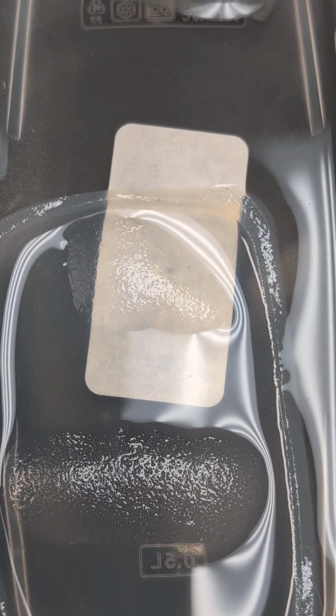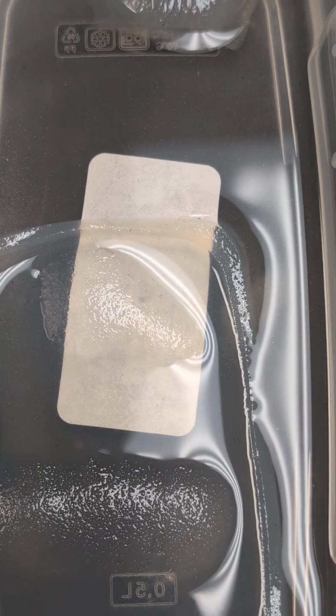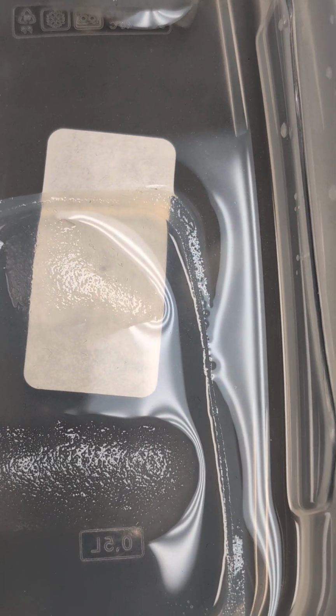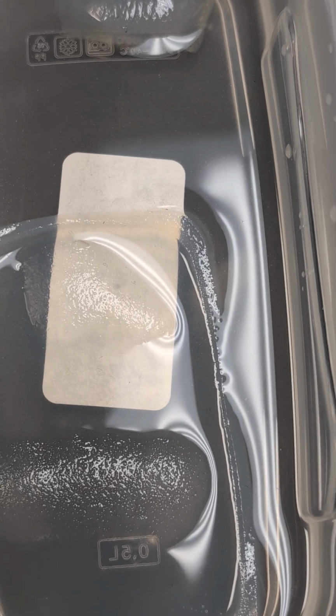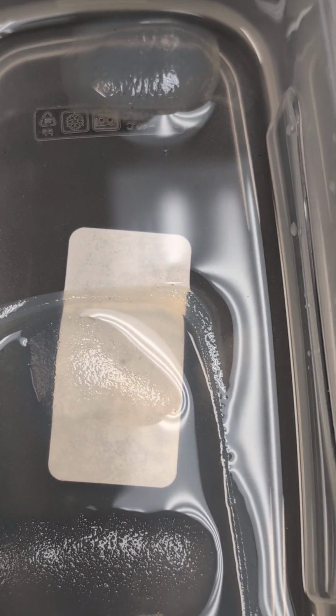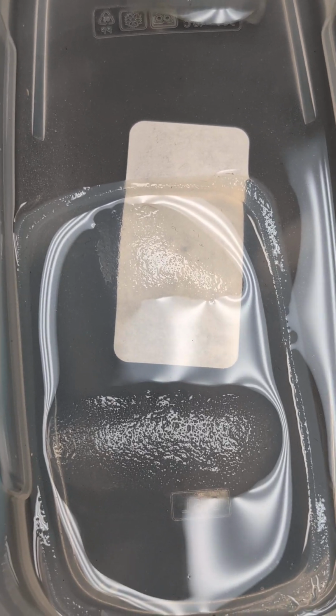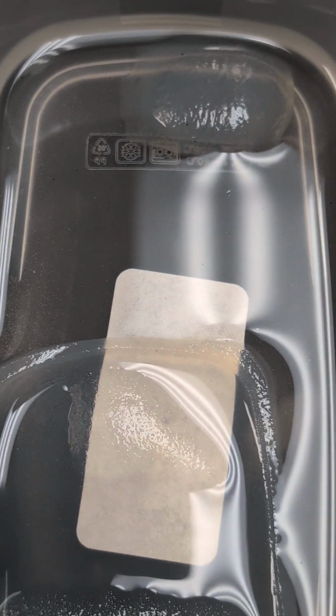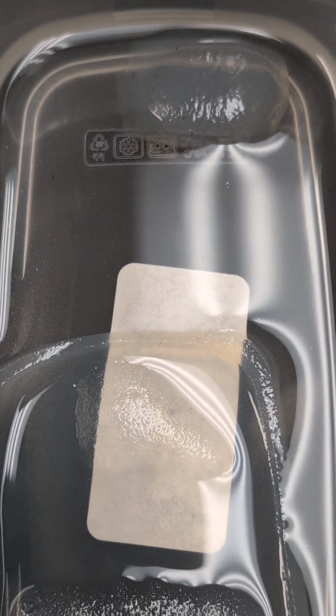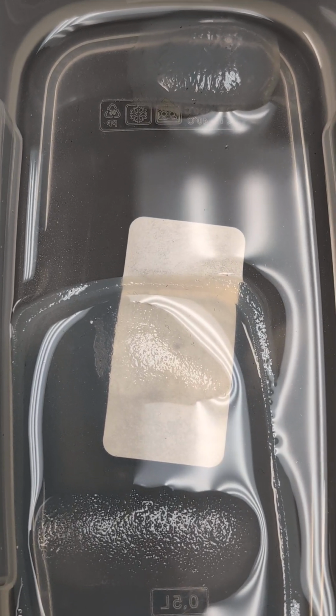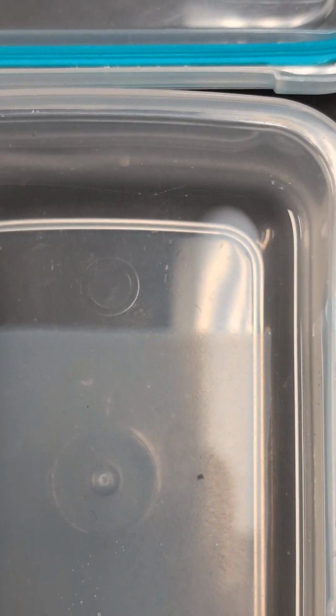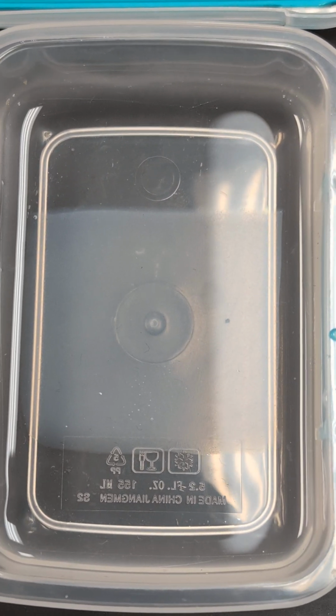And what's interesting with the glutaraldehyde, the chemical reactions between the Agar Agar carbohydrate alcohol groups, OH groups, and the dialdehyde, glutaraldehyde, you're forming hemi-acetal and acetal linkages. They're reversible, and the important thing is the pH range. Now, this solution, when we first put it together, was about pH 3, the bath. So I brought that up to pH 6 using litmus paper, pH 6. And I think you want to stay pH 5 to 6.5. If you're too acidic or too alkaline, you're not going to get really too much cross-linking, I would imagine.